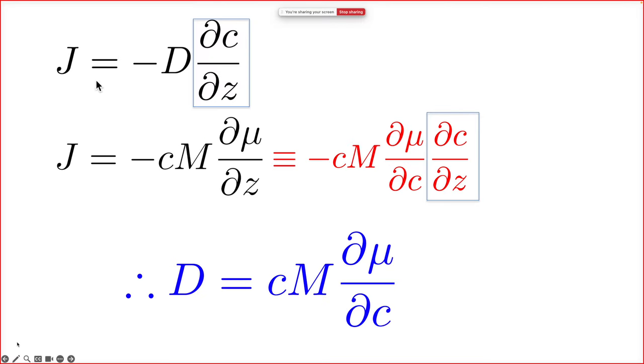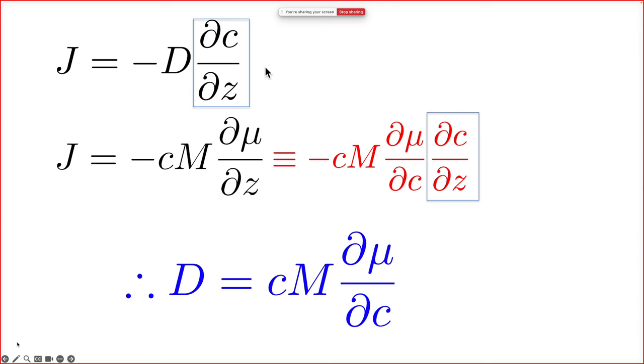To summarize: in the original Fick's law we have a concentration gradient, a diffusion coefficient, and a flux. Instead of the concentration gradient, we use a chemical potential gradient — a free energy gradient — with a positive constant called the mobility. We can expand this into two differentials and therefore write the diffusion coefficient as a function of the free energy gradient, the mobility, and the concentration. This is why we often express the diffusion coefficient as a function of concentration — it is no longer constant — but it still assumes the gradient does not matter apart from influencing the magnitude of the flux. I want to show you today that that is not the case.